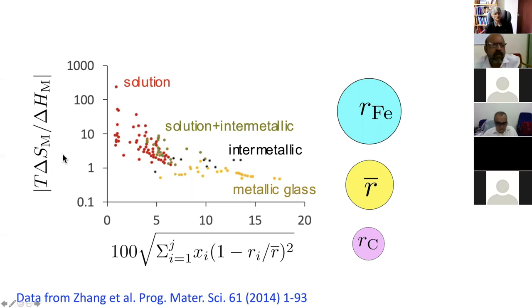And this is the ratio of the contribution to the free energy of mixing from the entropy of mixing, ideal entropy of mixing, and the enthalpy of mixing. And when it's one, these are similar, and of course when this is large, that means the entropy of mixing makes a huge contribution.